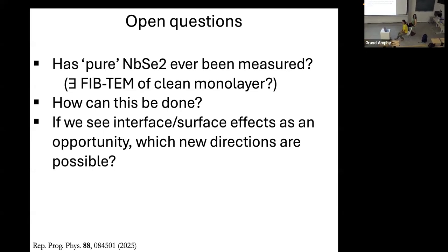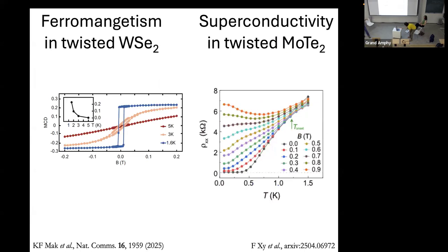How robust is this interpretation of the experimental signature of ferromagnetism? Because there is this whole story of ferromagnetism and superconductivity in LAOSTO, and there are quite a few papers around 2010 to 2012 where hysteresis in the critical field data was seen, and it was believed that some groups were having ferromagnetism and superconductivity together, but then these are not reproducible, and probably these are impurities. So how robust is this interpretation of calling it ferromagnetism? I'm not an expert in this, but at least what I understand is that they measure